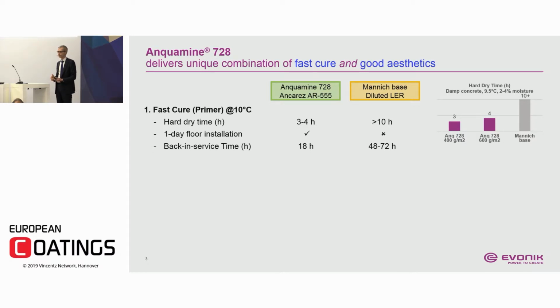So at ambient you will have your 3 to 4 hours, but at 10 degrees you'll really have that longer period of time. And typically a workforce, job applicators, will tell you that they will wait at a job site for a system to cure for 3 to 4 hours, but not longer. If it's longer, they will come back next day.